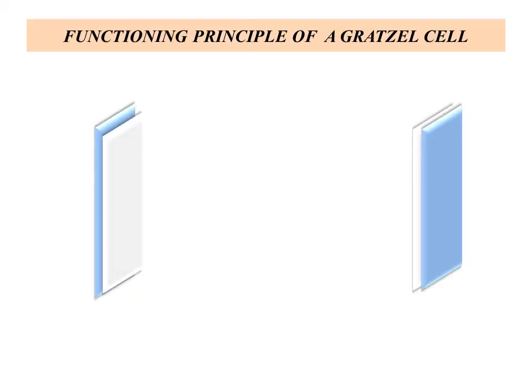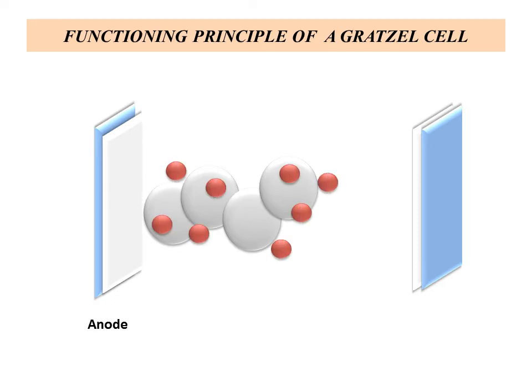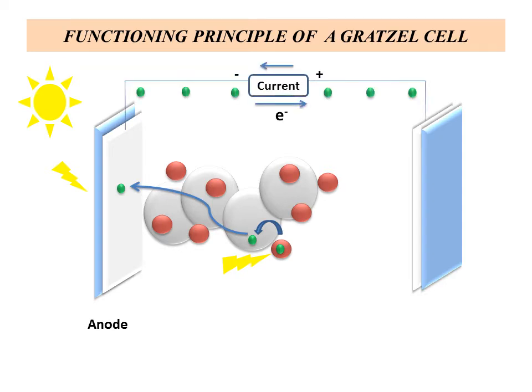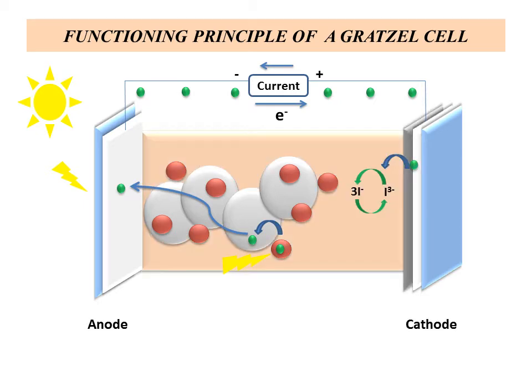The energy harvesting mechanism is based on the absorption of light by means of a dye molecule anchored on the surface of a porous wide bandgap semiconductor. Electrons are injected into the conduction band of the semiconductor and collected at the transparent conductive oxide electrode. The cell is completed by a cathode covered by a thin layer of gold and platinum, and it is filled with an electrolytic solution that closes the circuit, regenerating the dye molecule.